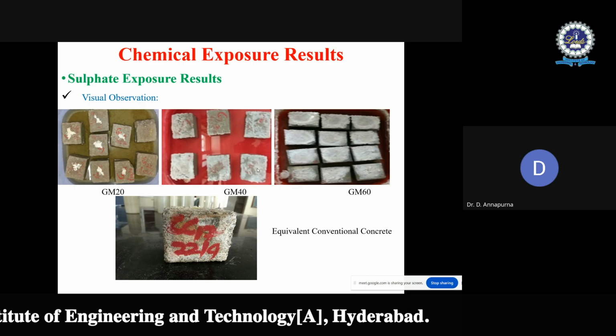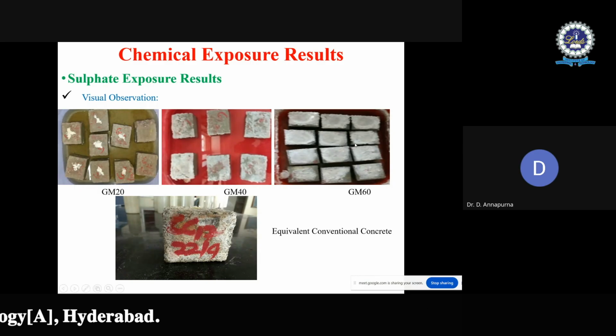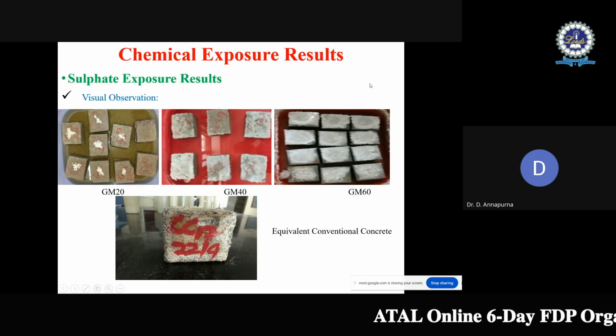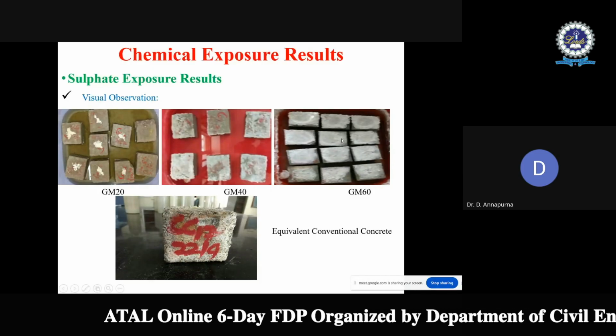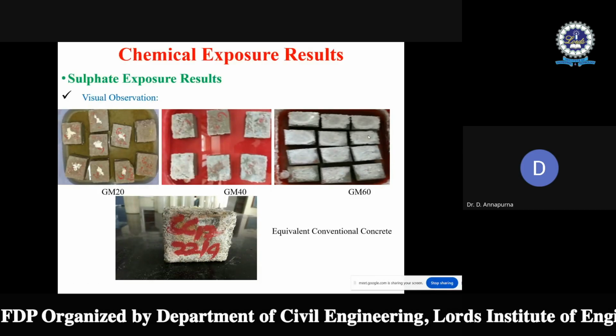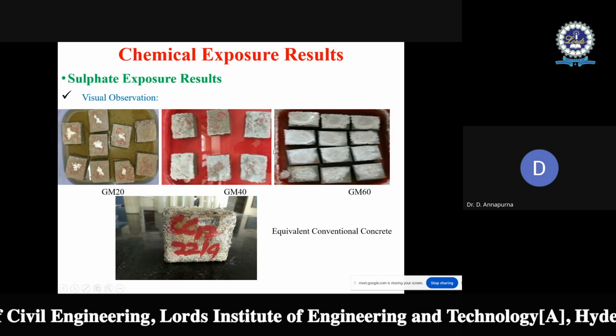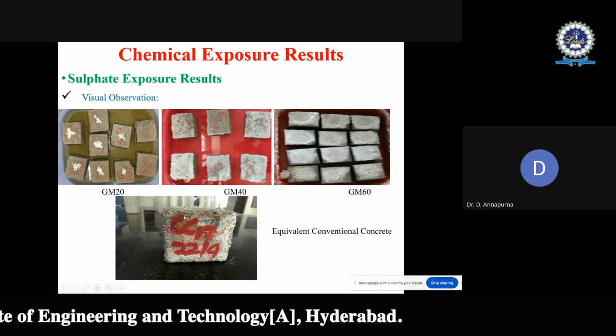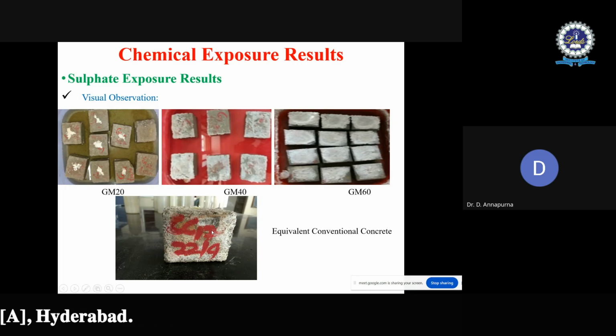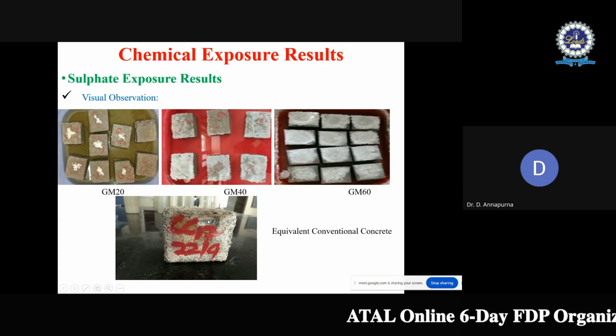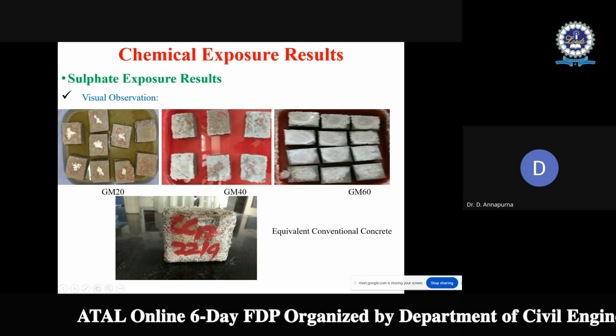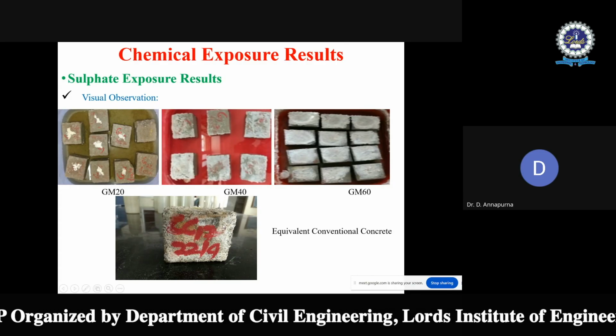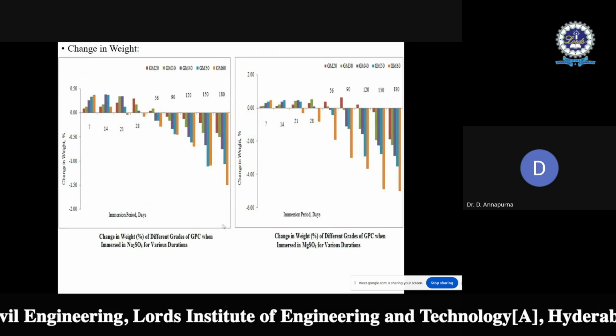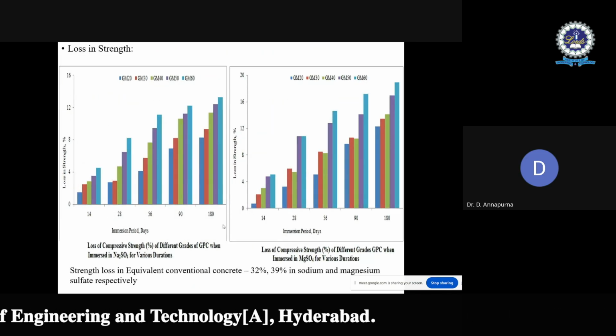So it is witnessed, if you look at these GM60 samples, the surface is almost covered with white patches after 56 days of exposure. These samples are taken after 56 days of exposure with little surface degradation. Surface degradation is not seen clearly. But when we see ordinary Portland cement concrete, significant white patch formation along with surface degradation is seen on this conventional concrete. So geopolymer concrete is showing superior behavior compared to the conventional concrete when exposed to magnesium sulfate. Then the change in weight is considered, then the loss in strength is also considered.